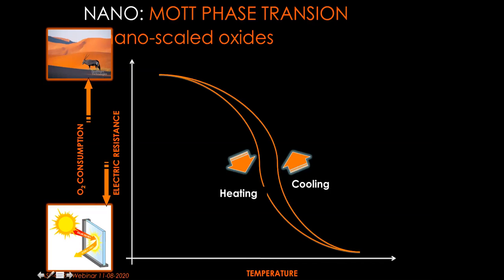There is a material which does this kind of thing. We call this hysteresis behavior. If you replace this oxygen consumption by what we call electric resistance, this material has this phenomenon. Its electric resistance changes like this. When it is cold, it is highly resistive. When it is hot, its resistance is very low. When the resistance is very low, we say it's metallic behavior. When the resistance is very high, we say it's insulating behavior.